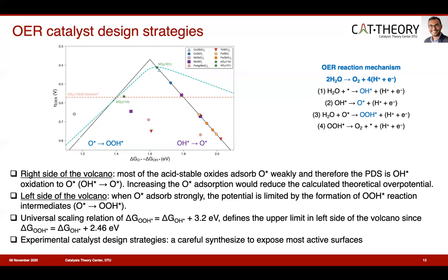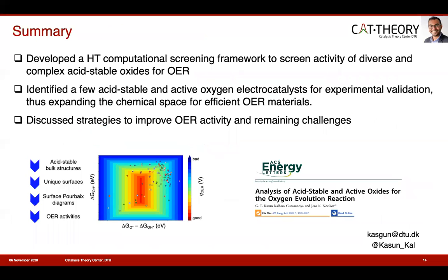We know from our previous slides that we have this universal scaling of ΔG_OOH equal to ΔG_OH plus 3.2. So for materials on the strong binding side, which is the left side of the volcano, this scaling relationship defines the upper limit for how efficient an OER catalyst can be, since the ideal scaling would be ΔG_OOH equals ΔG_OH plus 2.46. So to circumvent this scaling, an additional dimension of that site needs to be involved, which selectively stabilizes the OOH intermediate compared to OH. In summary, I showed the high-throughput computational screening framework we developed to screen the activity of diverse and complex acid-stable oxides for OER, which can be used to discover other functional materials as well.